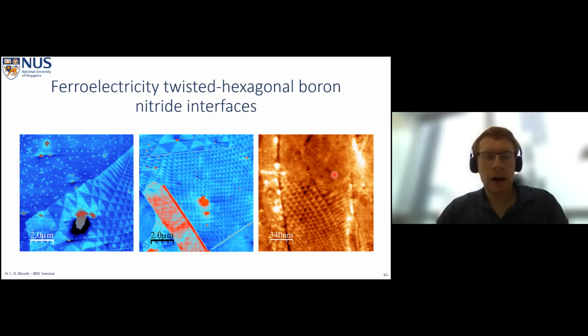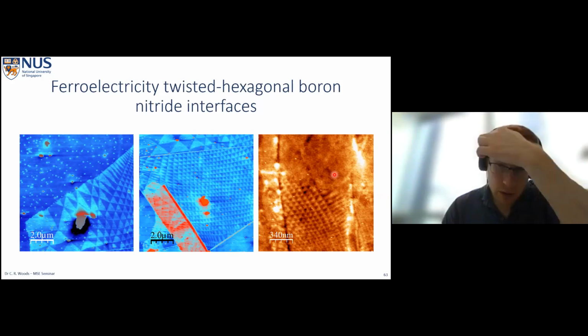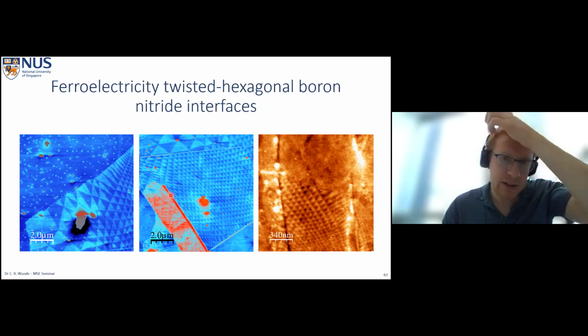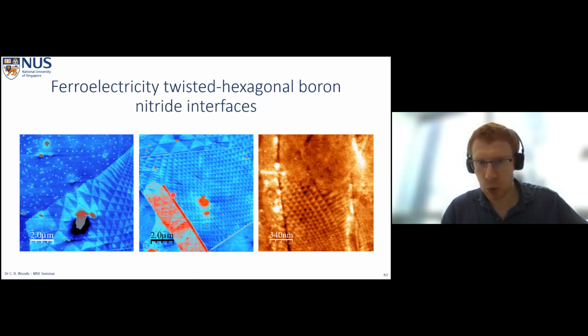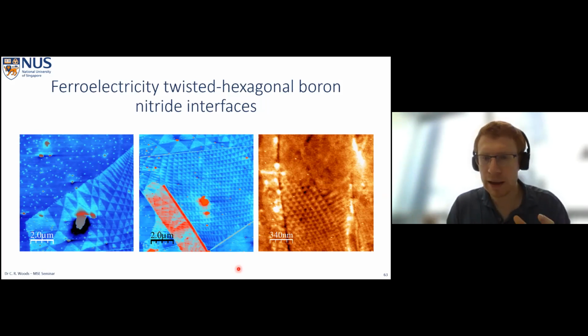Right, good question. So we deliberately made our samples. The sample that you're looking at on the left-hand side here is 4 layers of boron nitride on top of a thick boron nitride. So the inhomogeneity here comes from the fact that the 4-layer boron nitride has some macroscopic strain distribution in it.